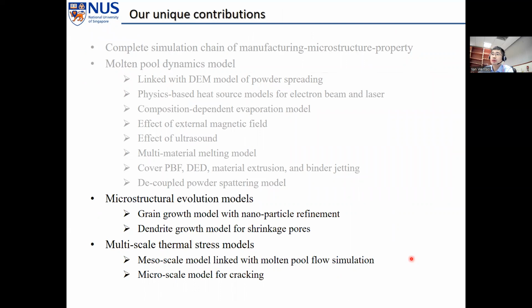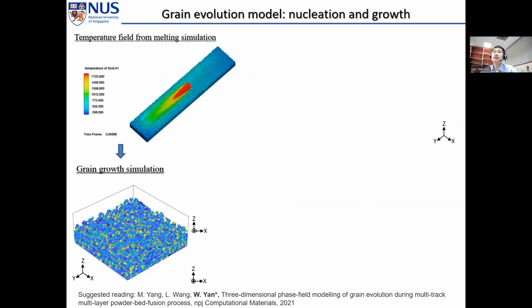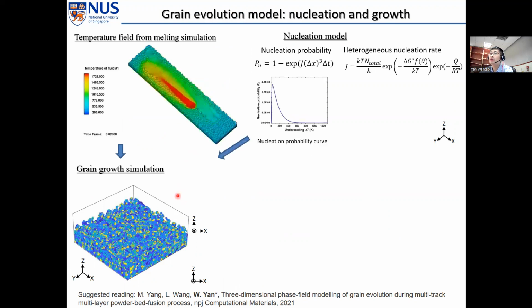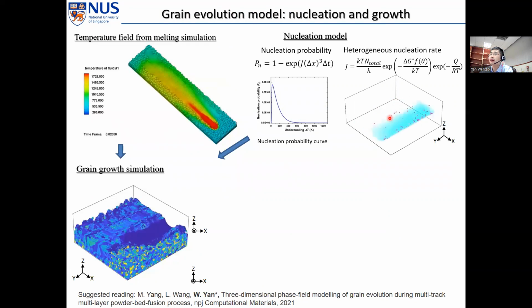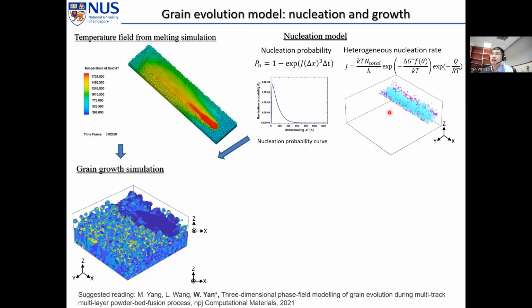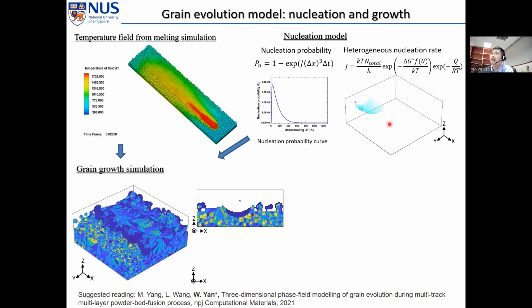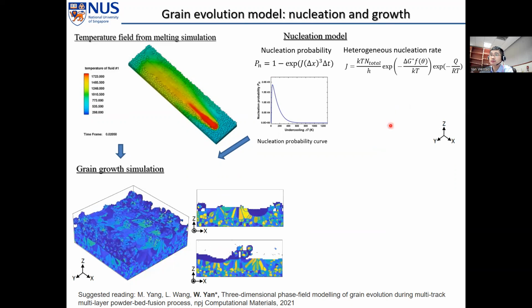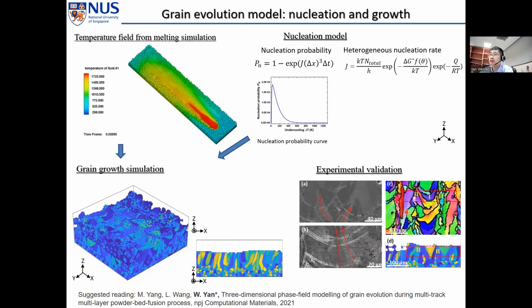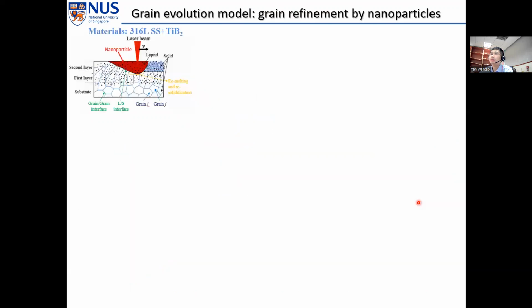And furthermore, we explore the microstructure evolution and thermal stress. The idea is simple. We just implement the temperature profile from the powder melting model into the grain growth model. In this model, our unique contribution is that we comprehensively incorporate a classic nucleation model, where these pink dots are the possible nucleation sites, and we implicitly track them so that we can consider the nucleation rather than pre-assign a nucleation seed. And these are experimental validation. The grain morphology and size all agree well with the experiments.